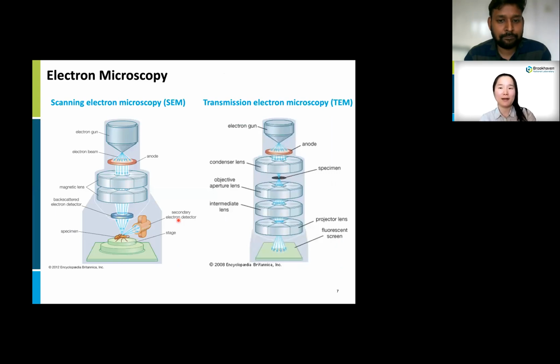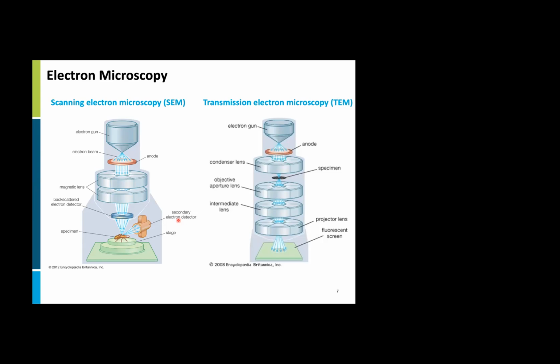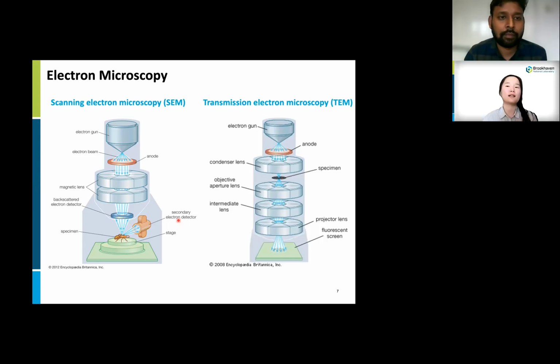There are two kinds of electron microscopes we generally use. One is SEM, scanning electron microscope, and the other is TEM, transmission electron microscope. SEM produces the image by scanning the surface of the sample with an electron probe, so we can see the surface topology. In TEM, we use the electron beam transmitted through the sample, and so we see a projected image of 3D objects. Here in TEM, the electron beam has to pass through the sample, so the sample usually has to be very thin, less than 100 nanometers thick.